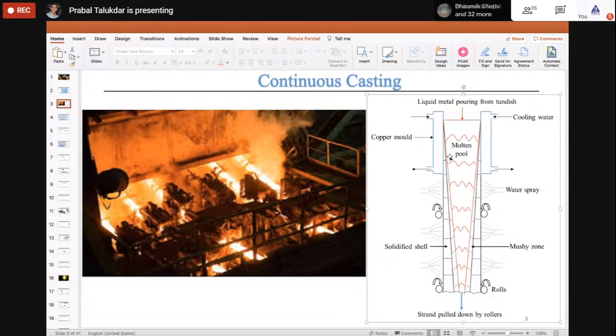Now what happens in this process, whenever the steel converts to solid, there is some shrinkage, right? Because liquid has a lower density, and when it becomes solid, its density is larger. Since density increases, it shrinks to a lower volume, and because of that, there is a gap formed between the mold wall and the solidified strand. If you see from this view, this is the complete length, but when it solidifies, because of the shrinkage, there is a gap found here.